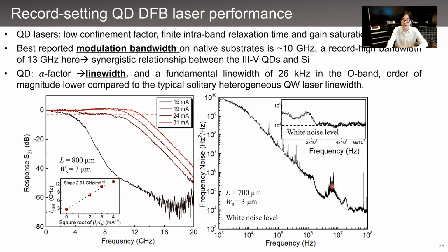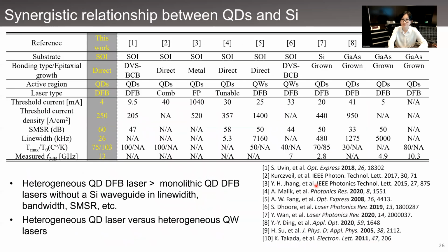Furthermore, one important aspect of quantum dot lasers is the small alpha factor that contributes to significant reductions in the laser linewidth. So here the Lorentzian linewidth was measured to be 26 kilohertz, which is an order of magnitude lower compared to the typical solitary quantum well laser linewidth, which is several megahertz.